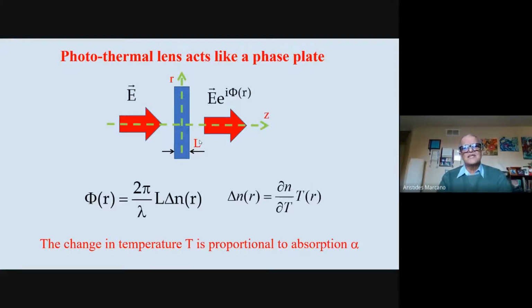Anyway, so we have this photothermal lens effect. We create some changes inside the refraction index because of the temperature. And those changes produce some field. There's a field of the refraction index, which can be understood as a lens. And that is like having some kind of phase plate. So you have a field represented by the letter E, an electric field, and after passing through your sample that has a length L, you can have that phase imprinted there. So you're making some kind of phase plate effect. And that phase plate, as I told you, is proportional to the changes in the refraction index, which are proportional to the temperature, so the temperature changes induced by the absorption.